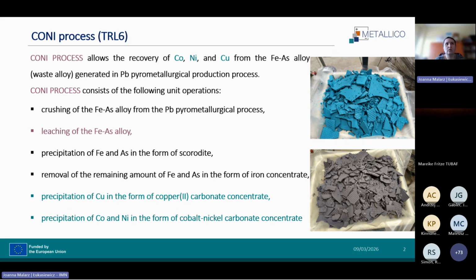The Koni process allows the recovery of cobalt, nickel, and copper from iron arsenic alloy, which is a waste product from lead pyrometallurgical production. The process begins with crushing the alloy to reduce particle size, followed by leaching to dissolve the metals. Iron and arsenic are precipitated as scorodite, while the remaining amounts are removed as iron concentrate. Finally, copper is recovered as copper carbonate and cobalt and nickel as cobalt nickel carbonate concentrate.